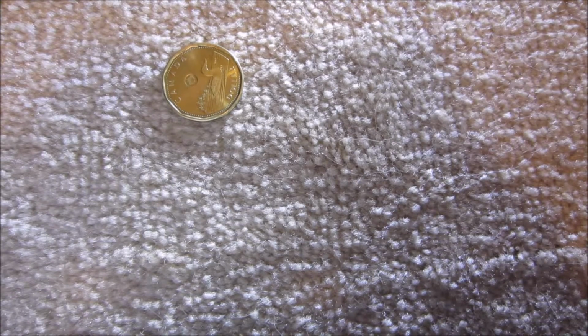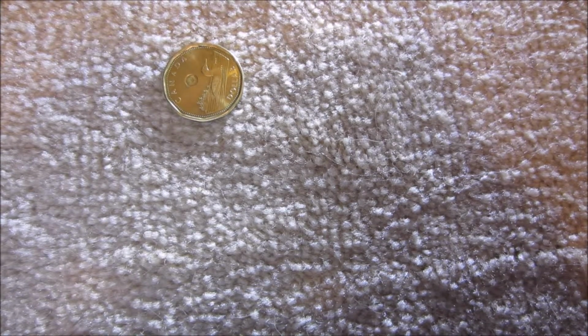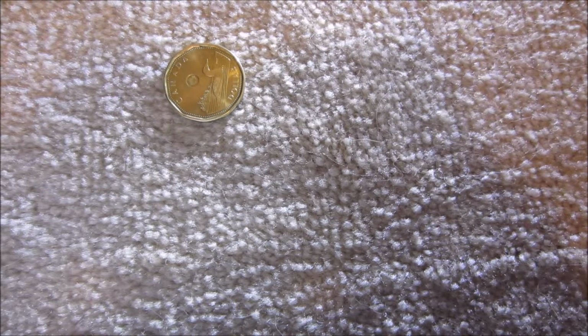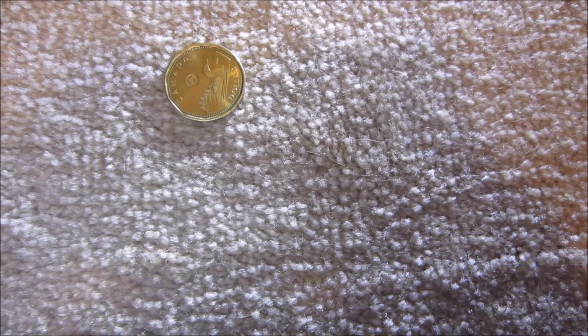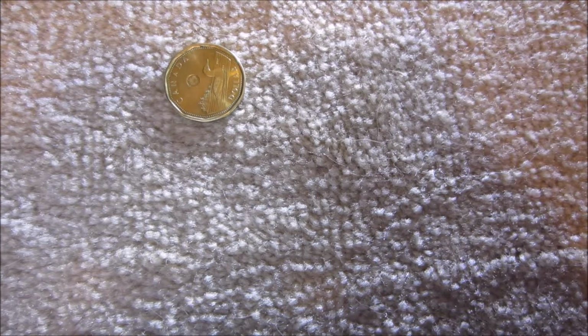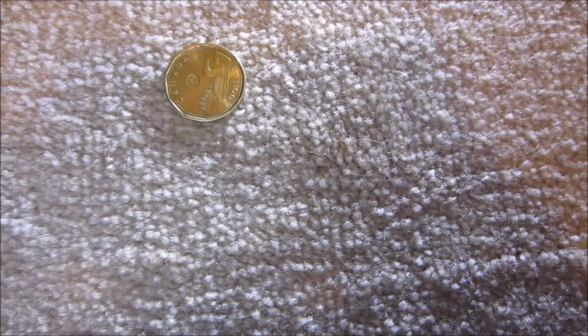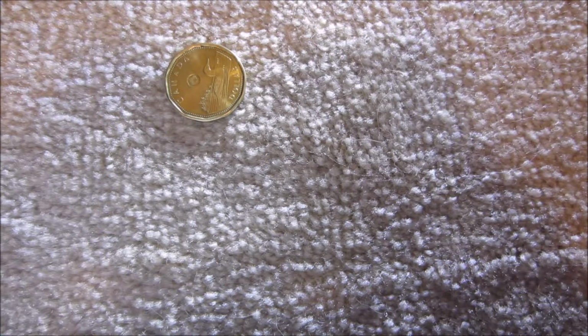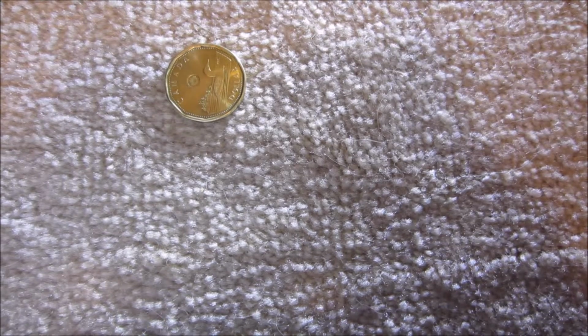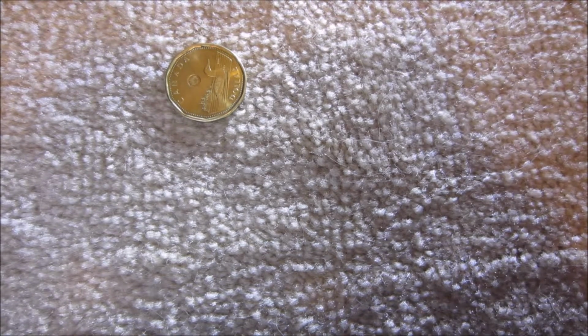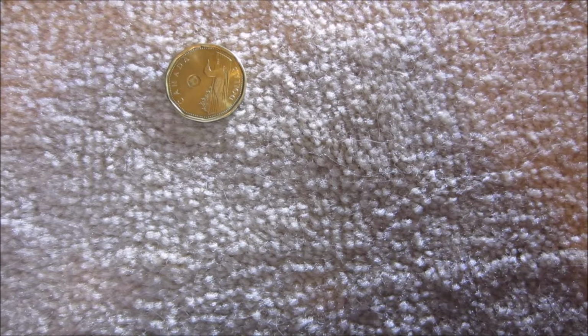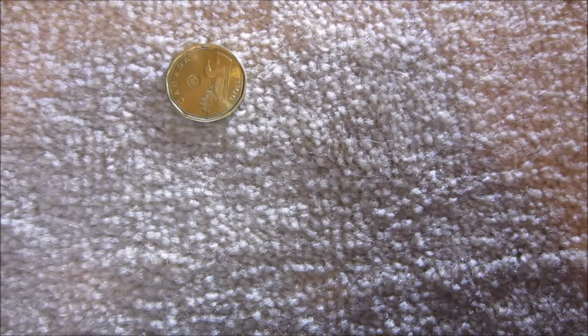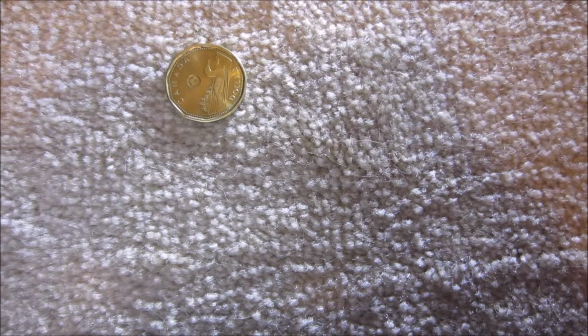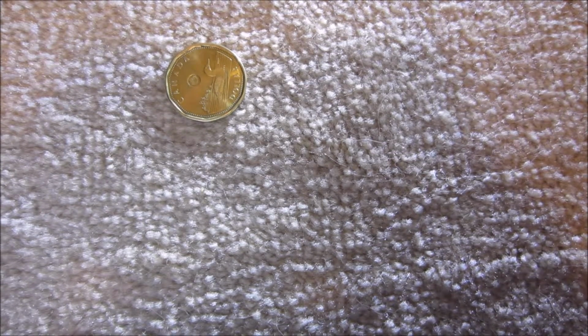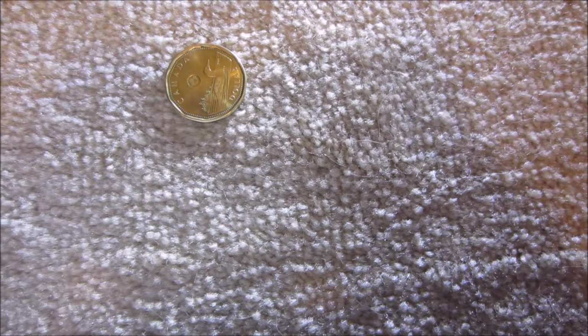Typically, a finished multi-ply product has an outer layer that is about 1.5 times harder than a monoply coin. MPPS technology allowed the mint to control the plating thickness of the alternating layers of brass and copper, providing greater flexibility in the development of the electromagnetic signatures compared to those generated by non-plated alloy coins of the same dimensions. Multi-ply coins provide 3 layers of metal coating, steel core, double anneal, superior quality and durability, shorter plating time, less expensive, and high security, unlike a monoply coin or paper dollar would offer.